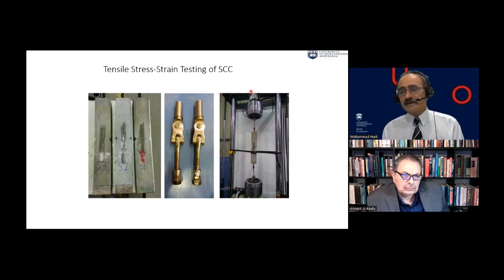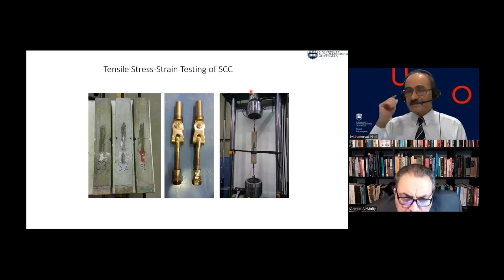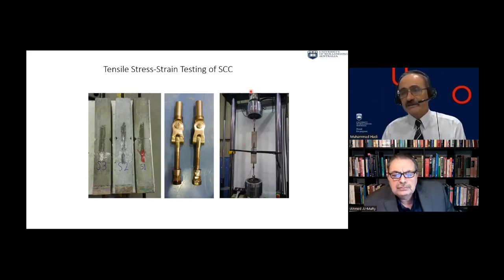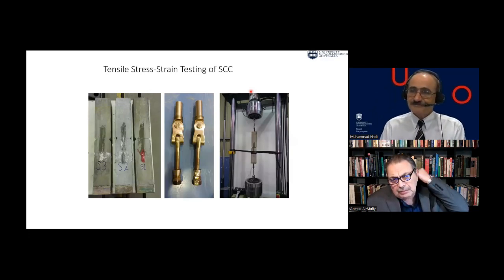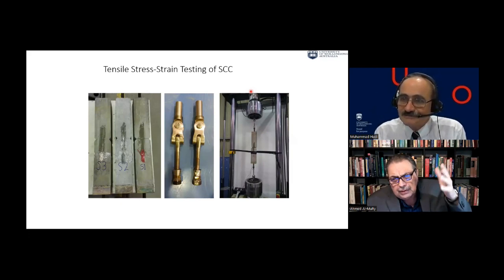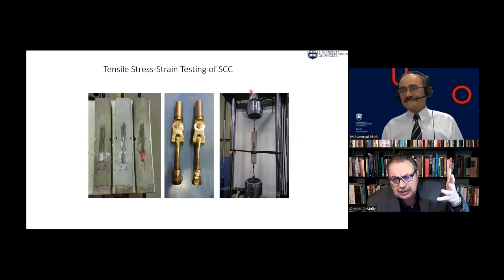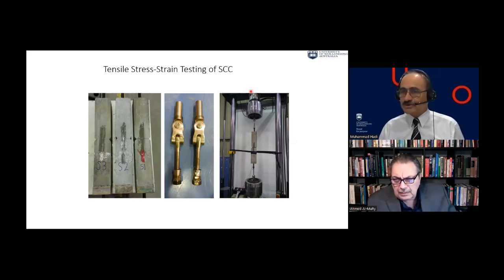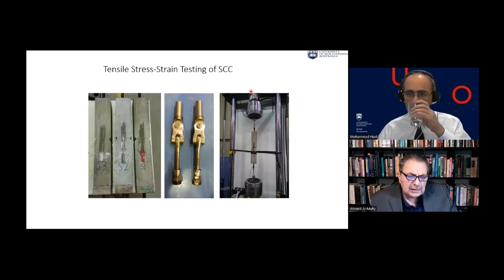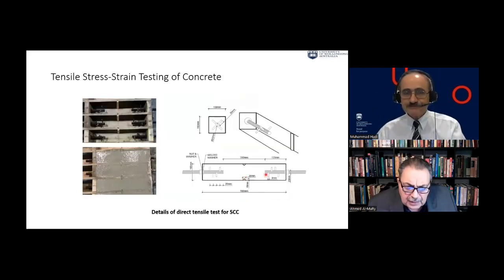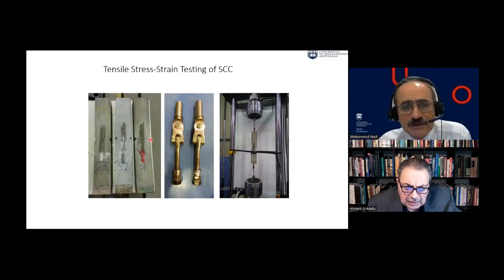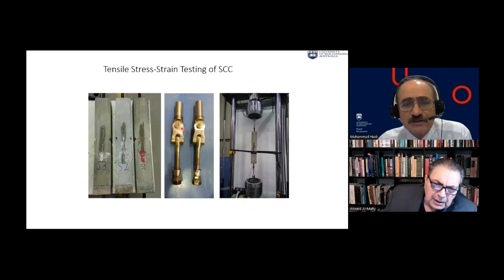And then we said, okay, let's send it to the ASTM journal to tell them that we have this, and we actually published it. It's really interesting. I would suggest that somebody should do some finite element analysis for crack propagation. Yes. Stress concentration in the notches. Near the notches. Yeah. The failure was good, because you can see it at the universal joint.